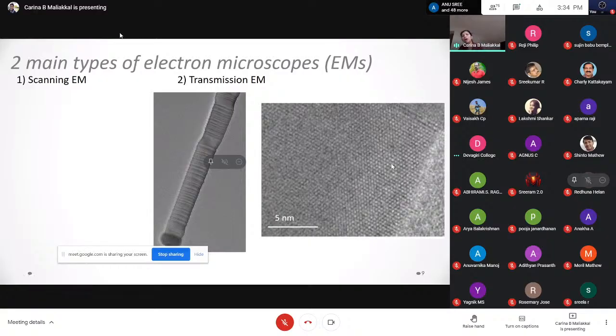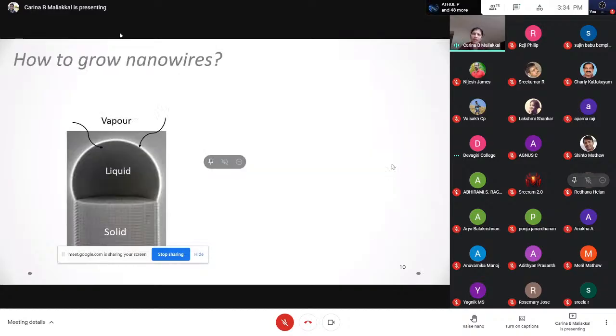Okay, so now how can we grow nanowires? Nanowires are usually grown by something called a vapor liquid solid mechanism. It means that, according to what material you are trying to make, you supply the precursors in a vapor phase, okay? And you use a liquid catalyst. This liquid catalyst is a nanoparticle, and you use it for absorbing materials from the vapor.